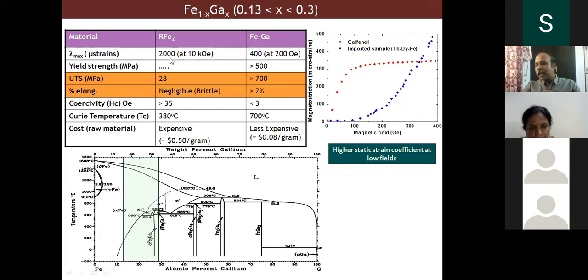That means essentially you can strain the sample with a normal toy magnet, whatever we are having. Okay, but to bias this material, we need an electromagnet or a big neodymium iron boron magnet kind of thing. As I told you, the UTS, that is ultimate tensile stress, is only 28 here, but it is Fe-Ga, it is very high, it is 700. The percentage of elongation is not there at all. You cannot elongate the material, but it is more than 2%.